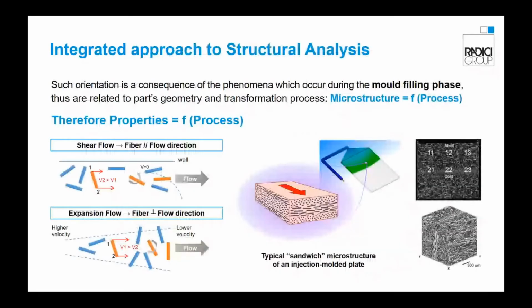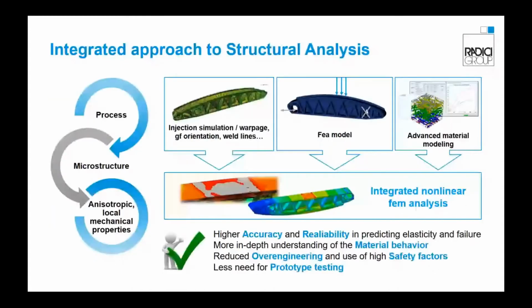But the orientation is a consequence of the phenomena which occur during the mold filling phase, thus related to the part geometry and the transformation process. So the microstructure is a function of the process. The integrated approach to the structural analysis takes into account the process-induced properties in the structural simulation, giving a higher accuracy and reliability in predicting elasticity and failure of the parts.